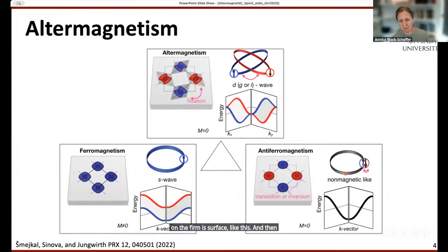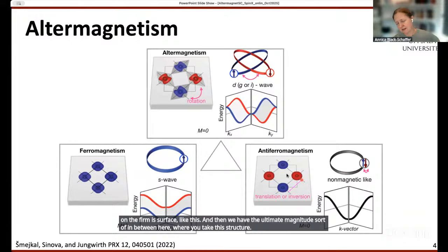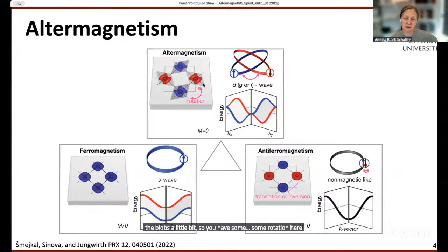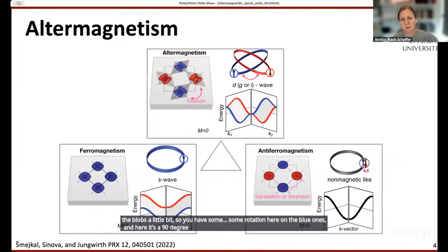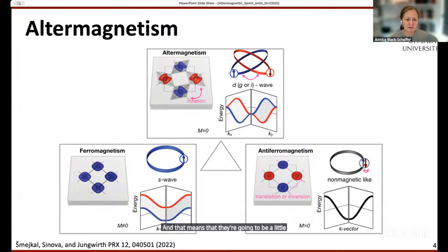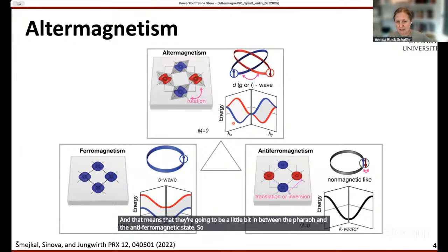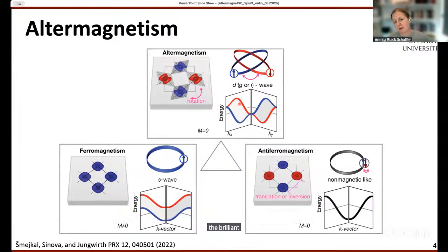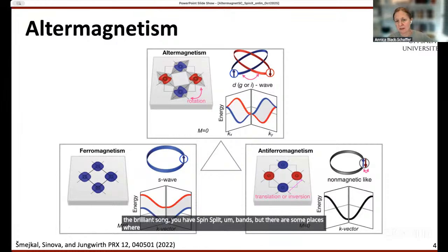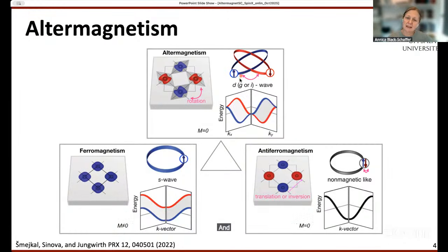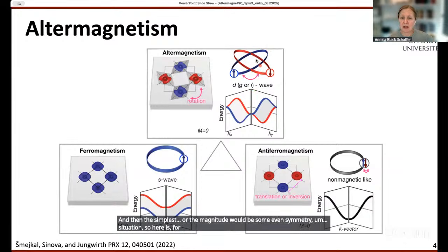And then we have the altermagnet sort of in between here, where you take this antiferromagnetic structure, I like to think about it this way, and you rotate the blobs a little bit. So you have some rotation here on the blue ones, and here it's a 90-degree different rotation on the red ones. And that means that they're going to be a little bit in between the ferro and the antiferromagnetic state. So in most places in the Brillouin zone, you have spin-split bands, but there are some places where you have a spin degeneracy. So now if you cut an energy somewhere, you can very easily get a Fermi surface that looks something like this. And in the simplest altermagnets, it would be some even symmetry situation. So here is, for example, a D-wave structure, but you can also have G and I-wave structures.